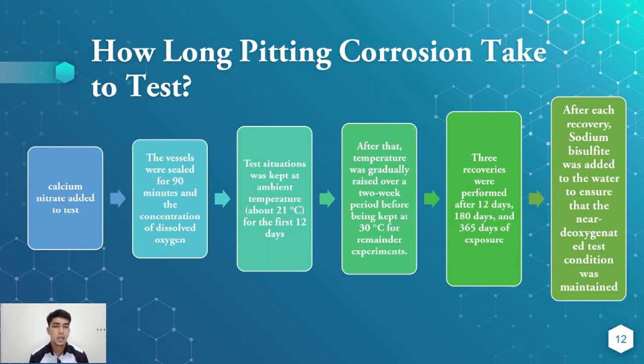Okay, these are some of the summaries of the pitting corrosion test. First, calcium nitrate was added to the test. After the calcium nitrate was added, the vessel was sealed for 90 minutes and the concentration of dissolved oxygen was measured. After the vessel was sealed for 90 minutes, the test solution was kept at ambient temperature, about 21